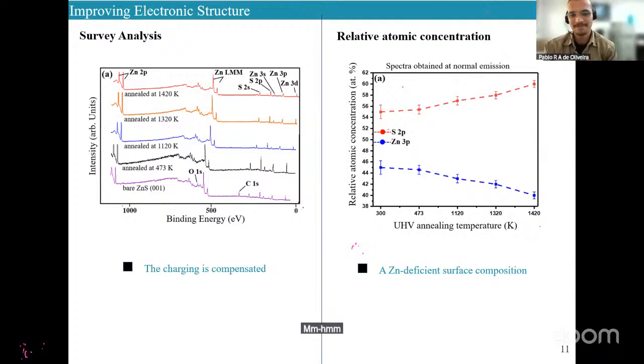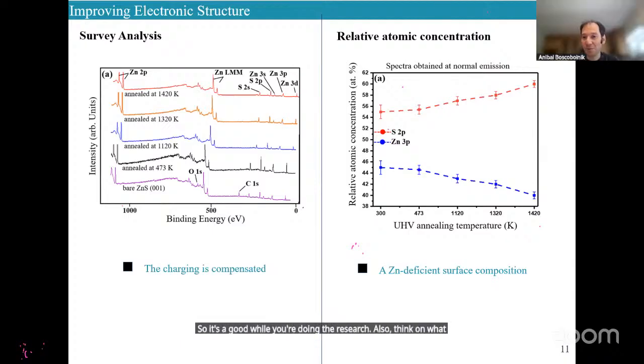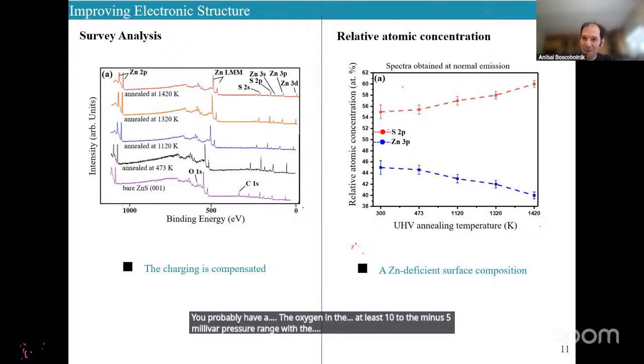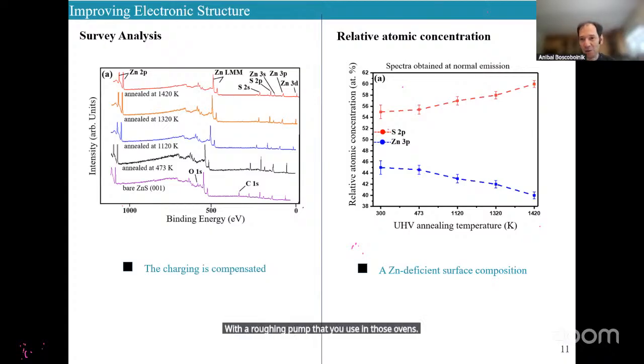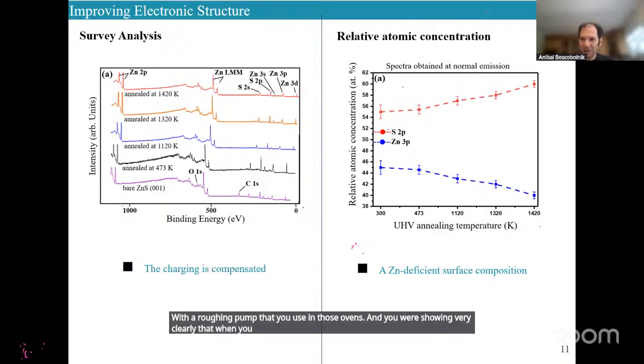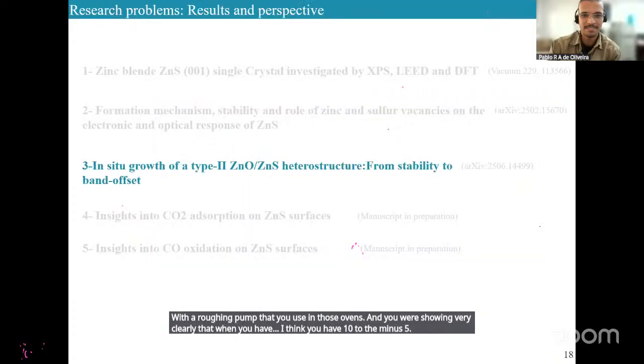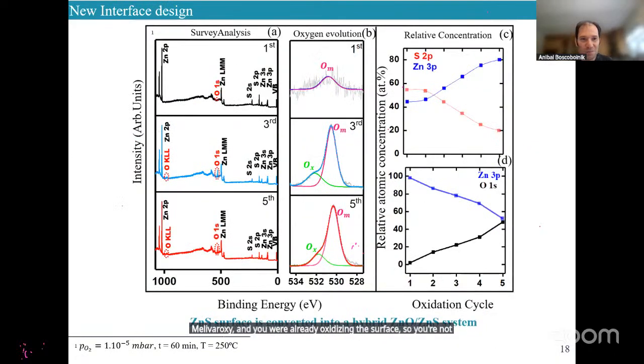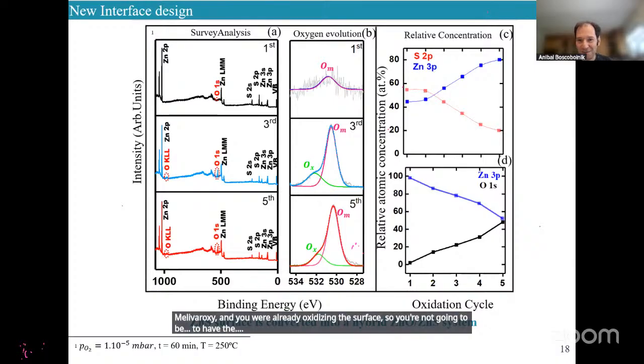So it's good while you're doing the research to also think about the implications, or what would happen if you had to scale this up. The ideas you were mentioning on the furnace are very reasonable. And as you mentioned, even if you have a vacuum furnace, you probably have oxygen in at least the 10 to the -5 millibar pressure range with the roughing pump that you use in those ovens. You were showing very clearly that at 10 to the -5 millibar oxygen, you are already oxidizing the surface, so you're not going to have your intended surface even when using that furnace.